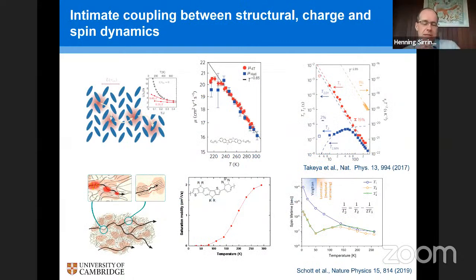The physics of these systems is quite different when you just look at, for example, the temperature dependence of the mobility in a molecular system. As I explained at the beginning, we see this band-like temperature dependence of the mobility, where the mobility increases with decreasing temperature. In a polymeric system, because of the residual energetic disorder that we have, typically the mobilities are activated. So it's not clear by looking at the temperature dependence of the mobility whether there are any similarities between molecular systems and polymers. But if you look at the spin relaxation behavior, which is in a sense a more local probe of the charge dynamics of these systems, you actually see quite a striking similarity.